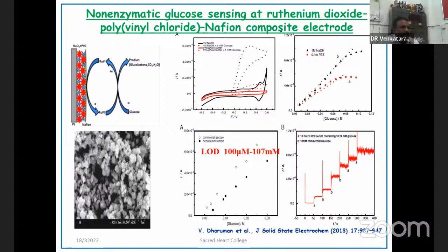Here you can see this black dotted line is the sensing current in the sodium hydroxide solution, whereas this red dotted line is in the phosphate buffer solution. Remember, the activity is quite lower when you decrease the pH of the measuring solution to 7 or 7.4. But we want to apply it for blood sample analysis. So we always characterize the system in phosphate buffer, and we take this potential as the maximum potential, and this potential as the constant potential for chronoamperometry, and we monitor by increasing the concentration of glucose in a drop-wise manner. You can see the linear range we get is around 100 micromolar to 107 millimolar. But here the problem was these results cannot be reproduced all the time.